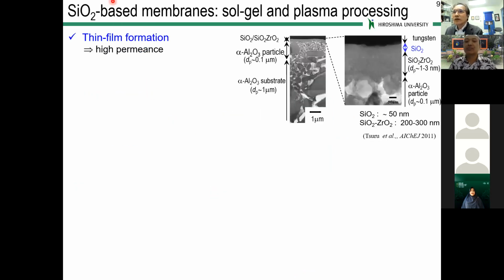Now, silica-based membranes can be prepared by sol-gel and also plasma processing, which have the advantage of thin film formation, which leads to high permeance. Here we have the TEM cross-section of our typical membranes, which was published in 2011.